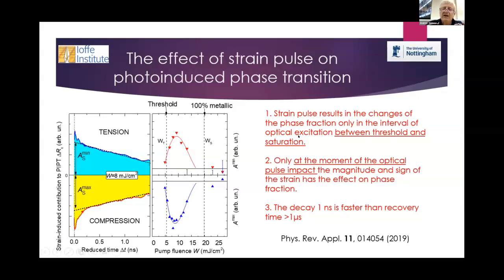So the important thing, and I would say the most interesting, is that only at the moment of the optical pulse impact does the magnitude and sign of the strain have an effect on phase transition. At other times it doesn't affect the phase transition.